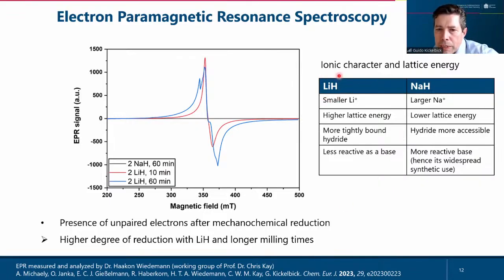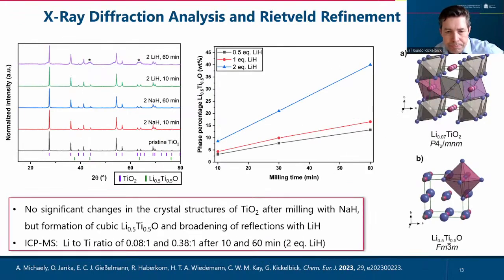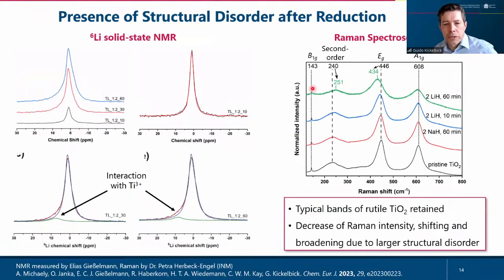And why is lithium better intercalated? This is clear because it has the smaller cation, sorry. This is a smaller cation. And we could prove that by different methods, not only by the Rietveld refinement, but also by ICP-MS, that lithium was intercalated in this reaction. Another method we often use here is solid state NMR. What does this tell us?